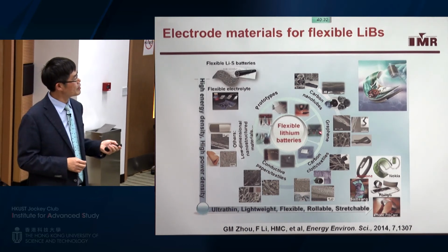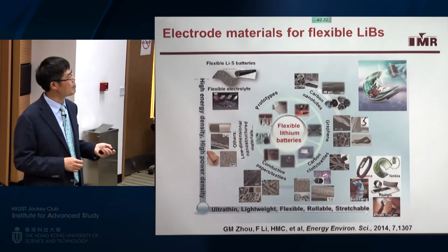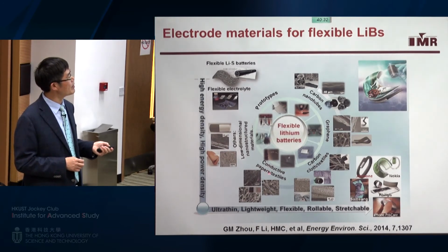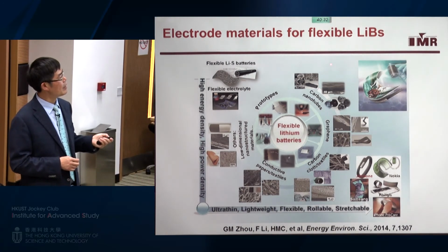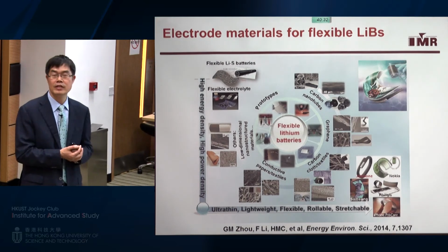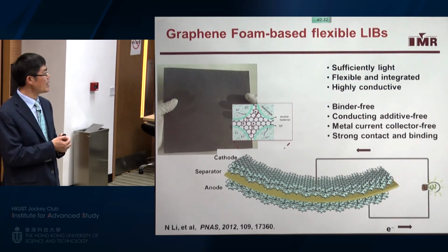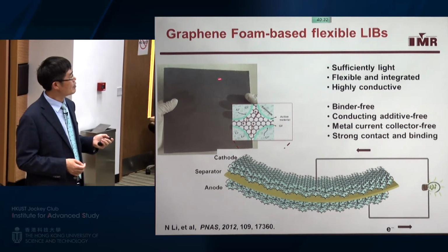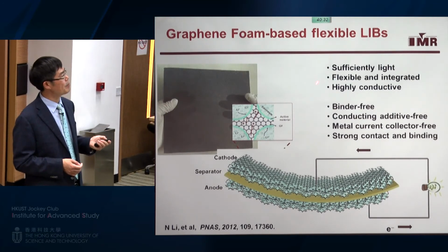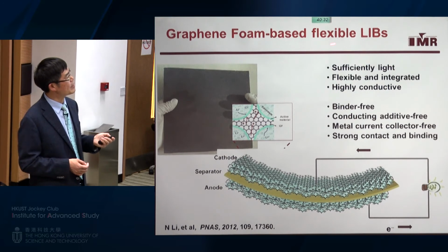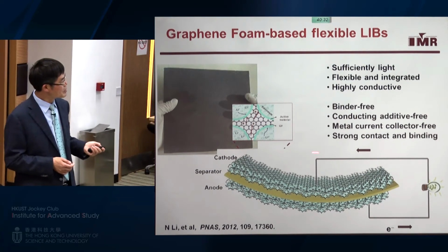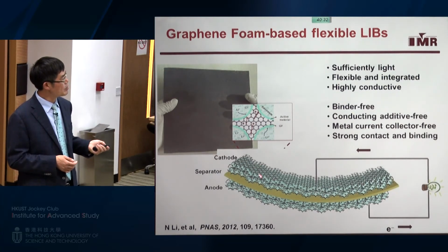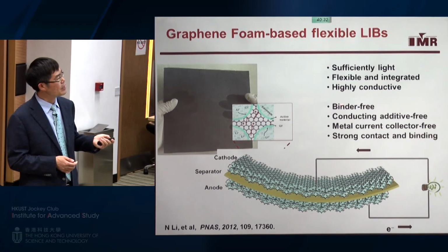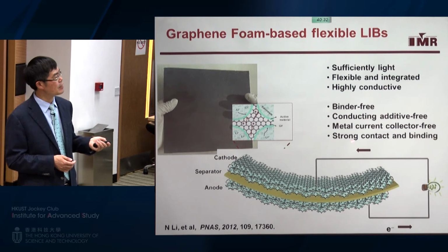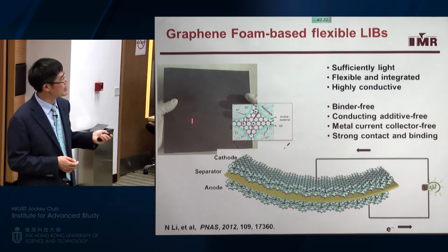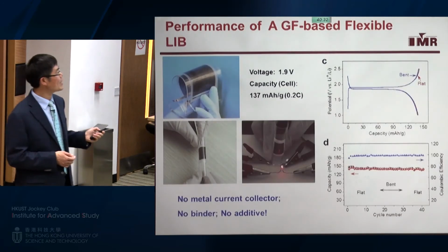In addition to carbon nanotubes and graphene, we can also use carbon cloth, carbon fibers, conductive papers, and so on to make different types of prototype flexible energy storage or flexible lithium-ion batteries. So we have also done some work. Again, we use this graphene foam as a substrate to make flexible lithium-ion batteries. Because we can incorporate the active material into this porous structure, we don't need to use a binder, we don't need a conducting additive, and we also don't need a current collector because this foam is highly conductive. So then we can make a battery.